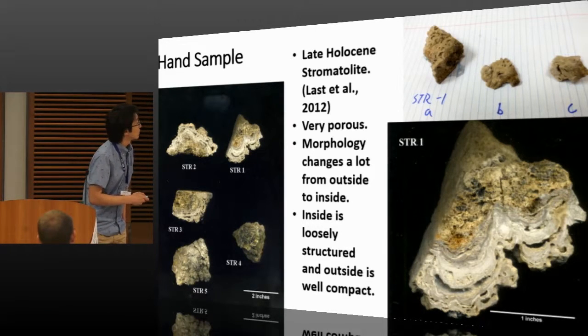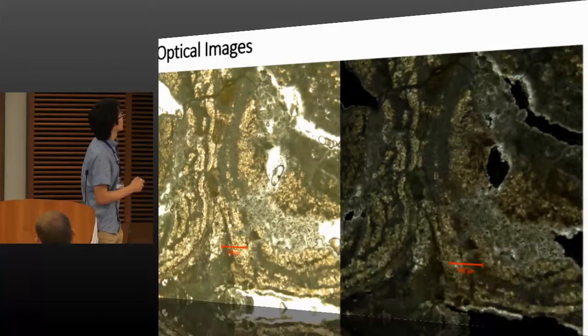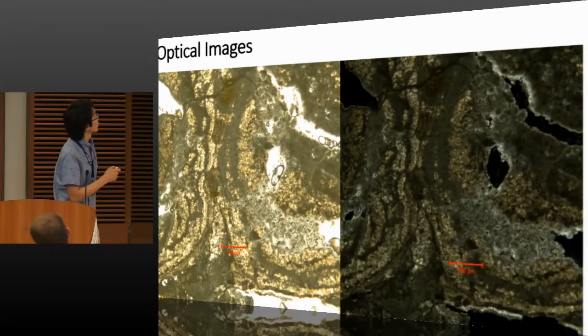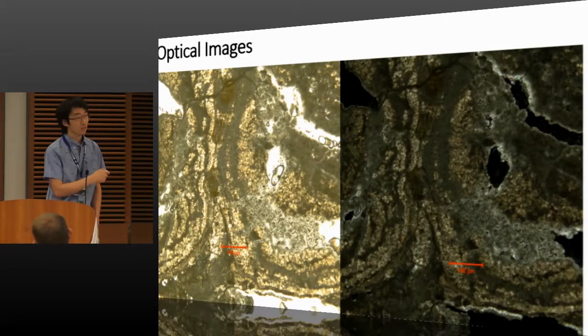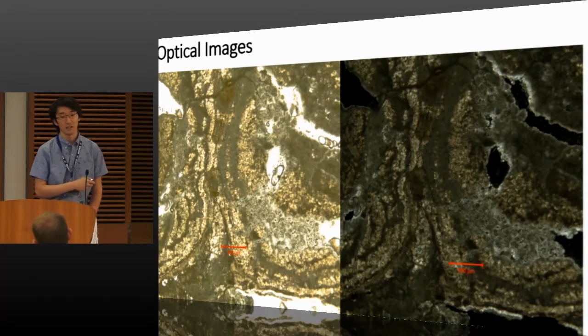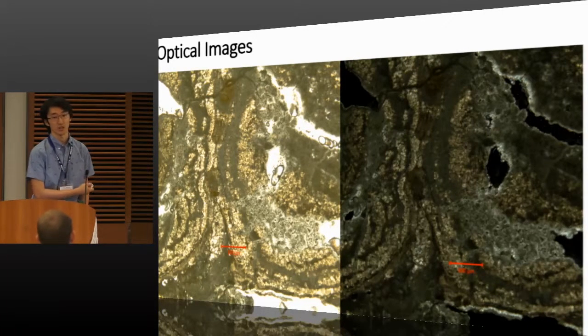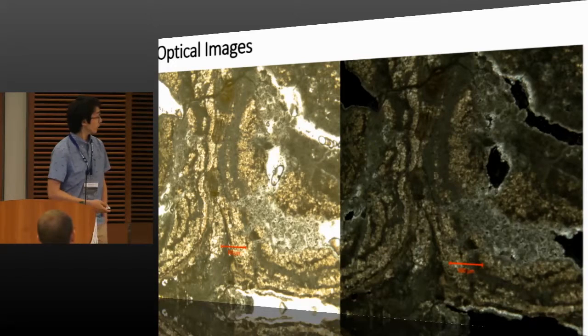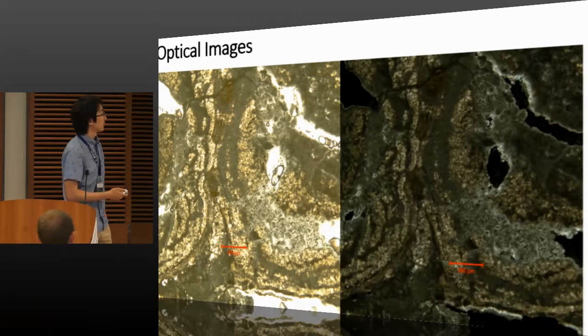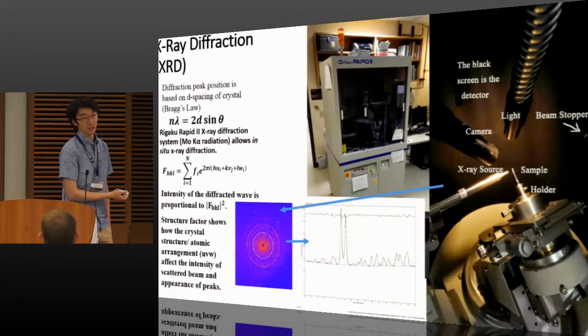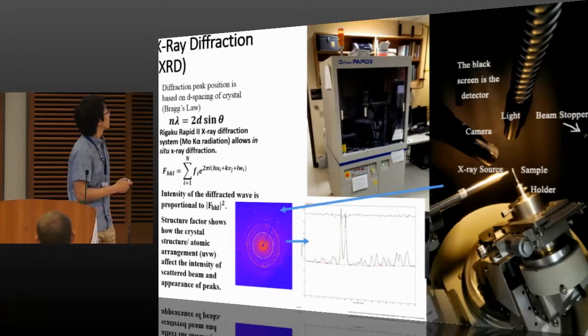And so this is the optical images. You can see more clearly now there's a really bright layer and then there's a dark layer. And then we think the dark layers are enriched in the organic material. But how are we going to test that? What if there is dolomite inside of it? So we use X-ray diffraction, XRD.